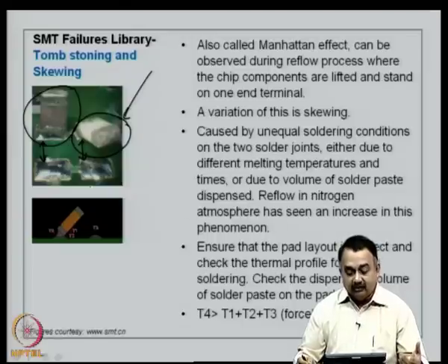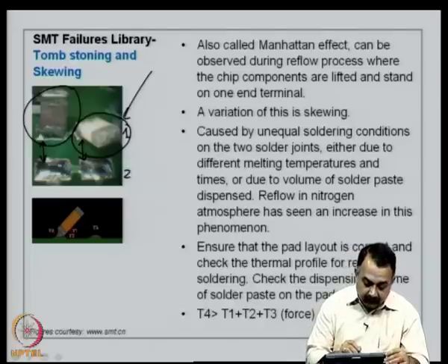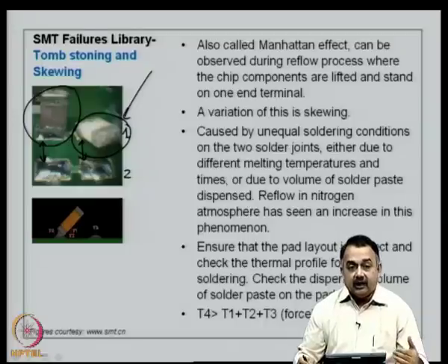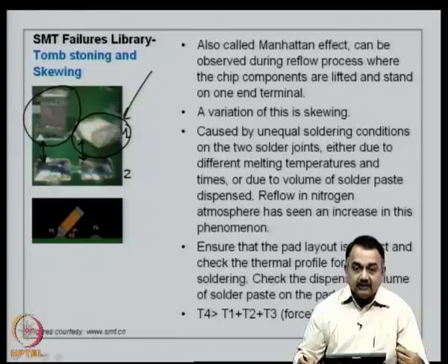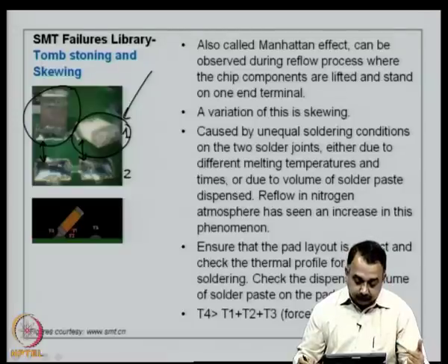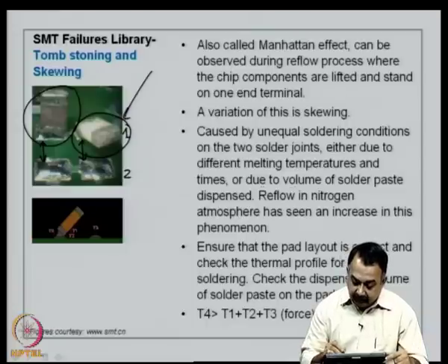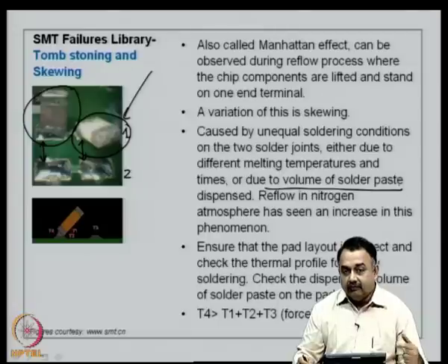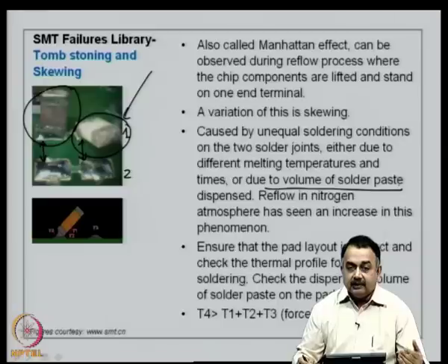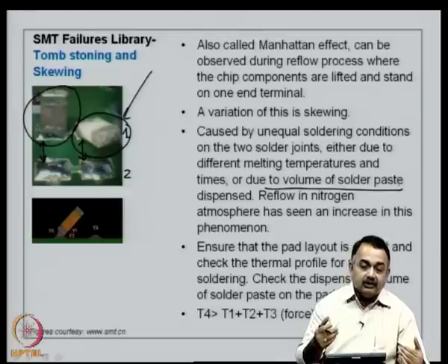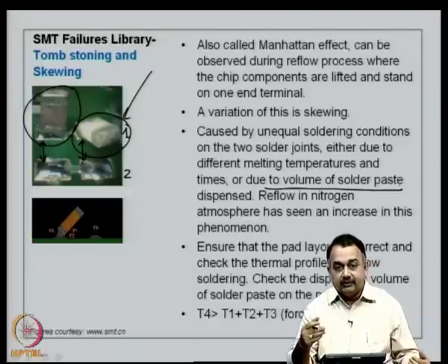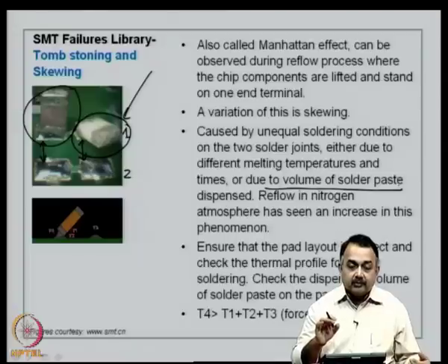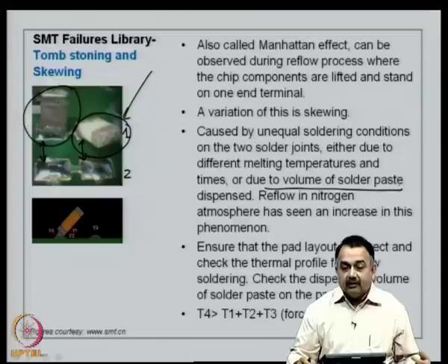This has happened either due to different melting temperatures on, let us say, pad 1 and pad 2, and also different times that you have given for the reflow process, or the time taken for the solder material that you have dispensed on the board to melt. This time has been unequal on the different pads. Now, this could also be due to different volume of solder paste that you have dispensed. Now, if you recall, solder paste is dispensed by syringe dispensing. For small prototyping you can do it manually, and that is where the problem comes. If you do manual solder paste dispensing using a syringe, you tend to have unequal volumes on the pad, and therefore these kinds of problems typically occur when you do manual syringe dispensing of the solder paste.